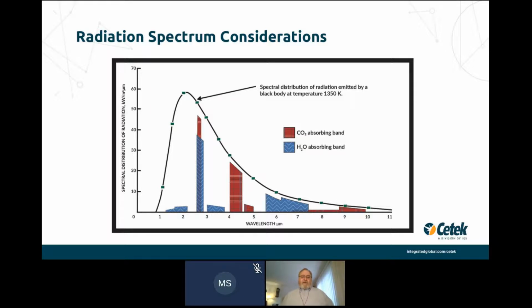The reason that the high emissivity coating is not used in oil-fired heaters is that this area underneath the envelope curve is more or less filled with different peaks. So the oil-fired flame, and the radiation from it, is very close to black body in the first place. So there's very little improvement in using a high emissivity coating in an oil-fired unit.